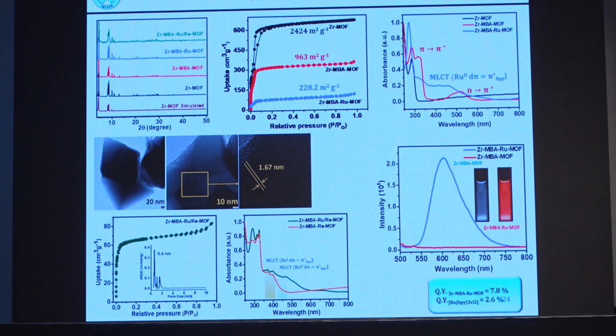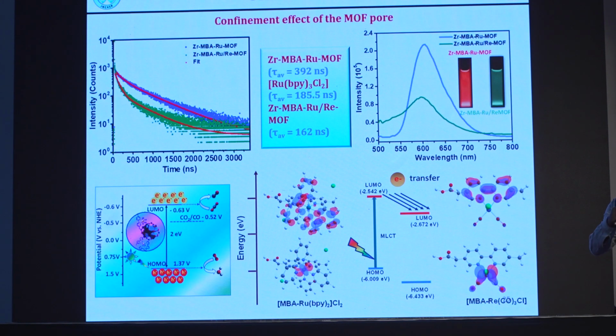So, fine. So what is the advantage I got? When I confine this kind of light harvesting moiety in the molecular container, you can see the lifetime of the ruthenium bipyridyl in the molecular state is 185.5 nanoseconds. But when you have zirconium MOF ruthenium, it's almost double. So when you confine such a molecular catalyst, covalently grafting inside the pore, what is it? You are reducing thermal vibration. Okay, so the non-radiative pathway decreases. So that allows the radiative pathway, that's why the lifetime is more.